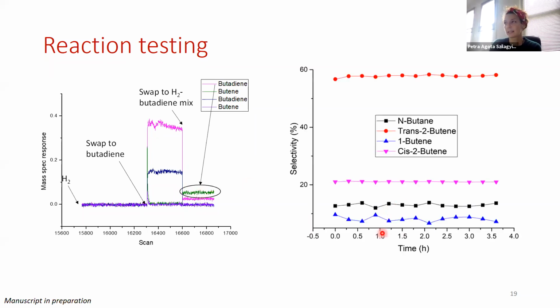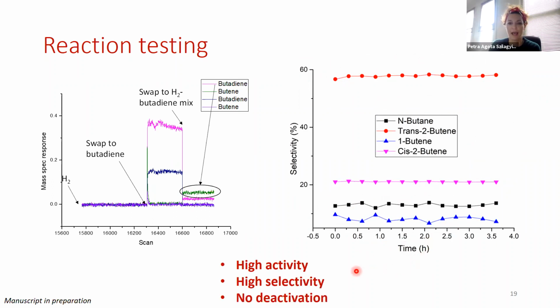We also looked at the selectivity as a function of time. And as you can see, it is really quite selective to the trans-2-butene formation. And there is only a very small fraction of butane that is formed. So the over-hydrogenation is really not that relevant here. So this is highly active, selective, and also quite stable.